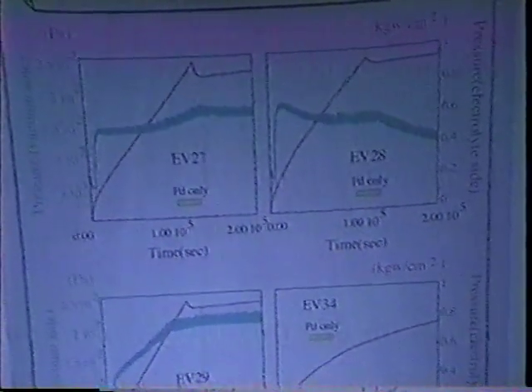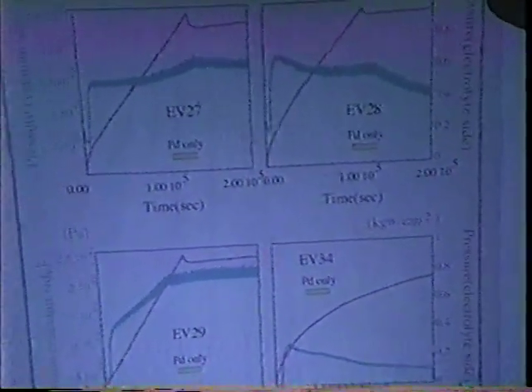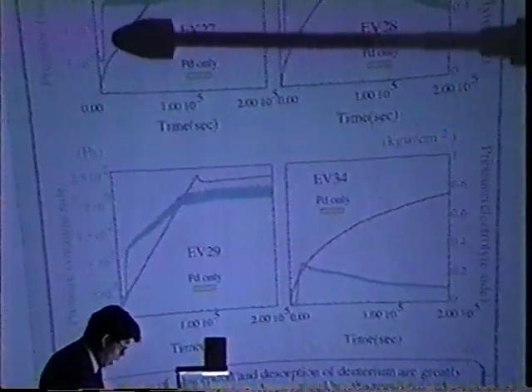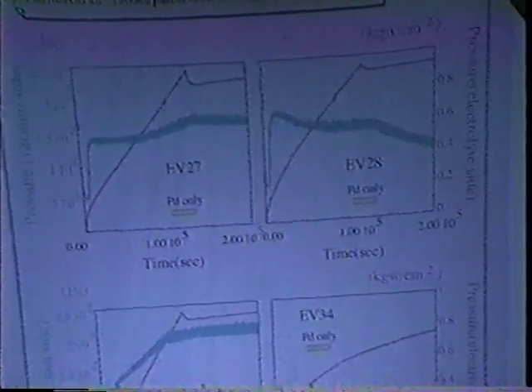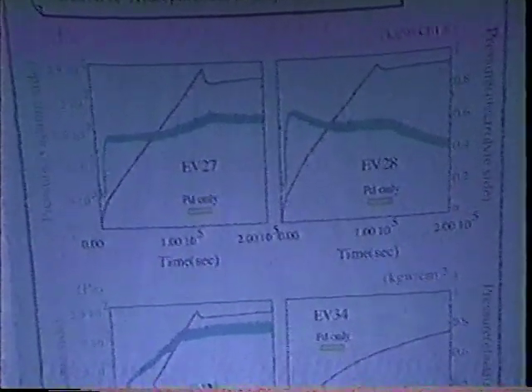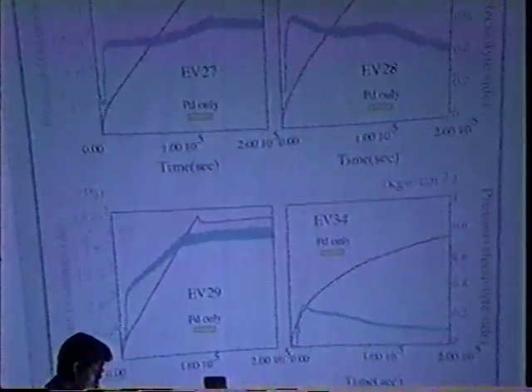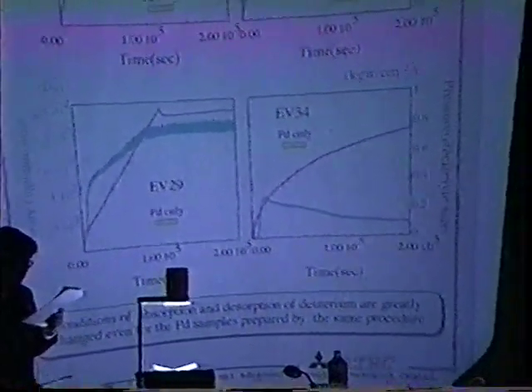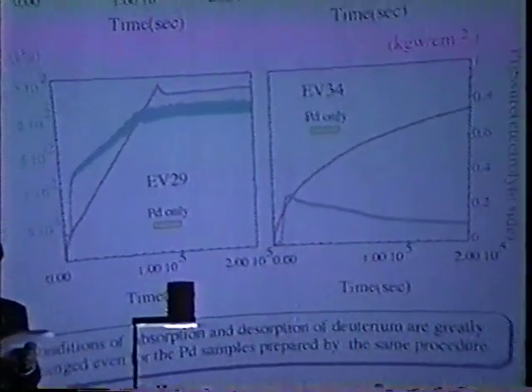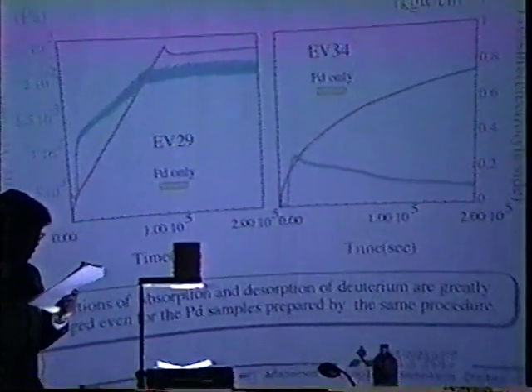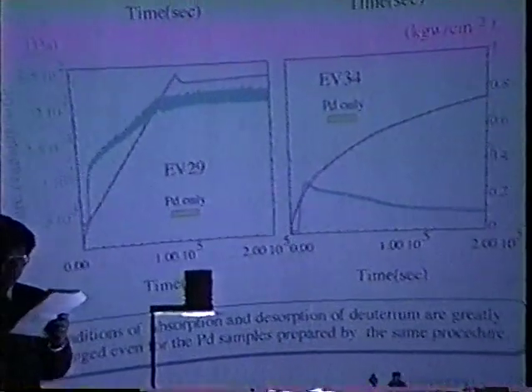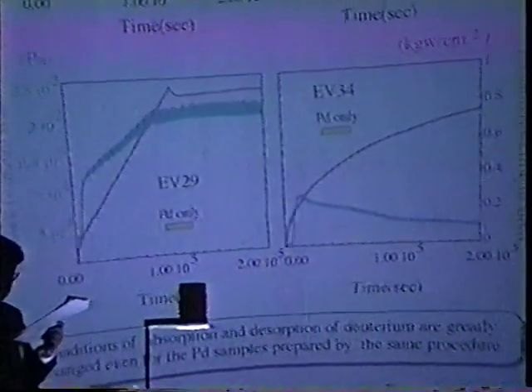This figure shows the variation of absorption and desorption of deuterium. In these cases, procedures of sample preparation are all the same. Horizontal lines mean the time, the pink line is the pressure of the electrolyte side, which corresponds to the quantity of deuterium into palladium, and the green line means the pressure of the vacuum side. It corresponds to the derivative of the quantity of deuterium released out from palladium. It is easy to see that conditions of absorption and desorption are greatly changed even for palladium samples prepared by the same procedure. It shows that absorption and desorption behavior of deuterium is greatly influenced by unknown factors, for example, impurity or surface condition of palladium.